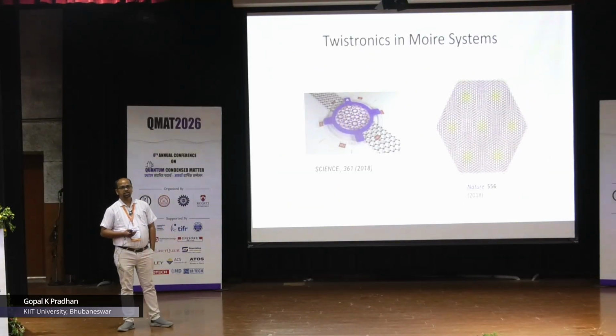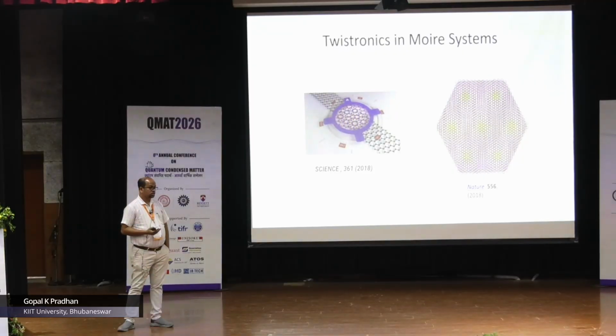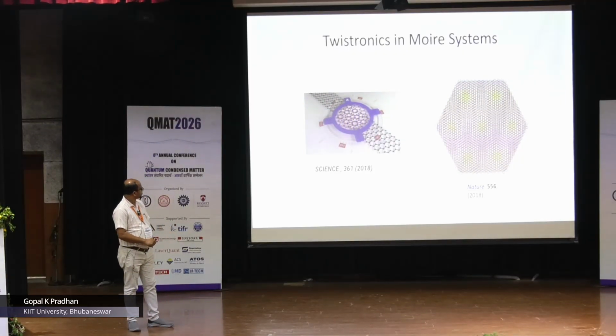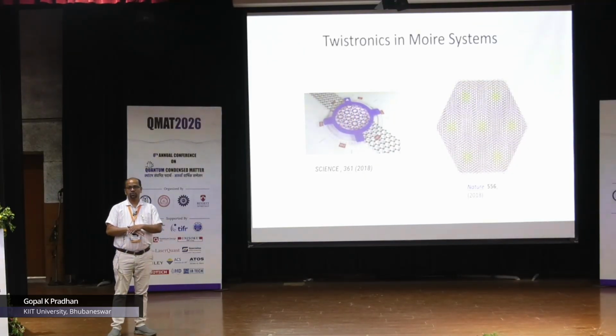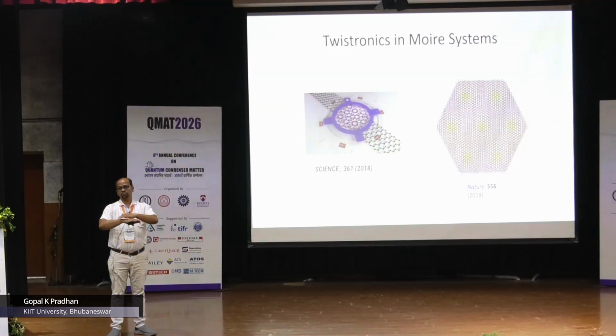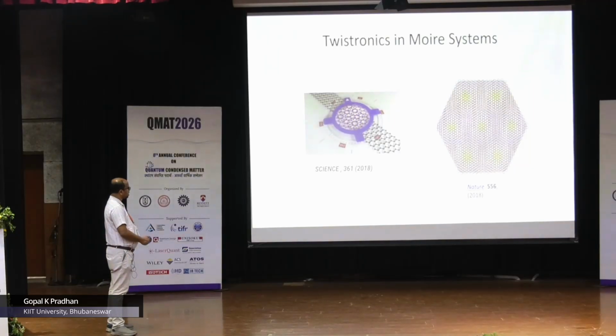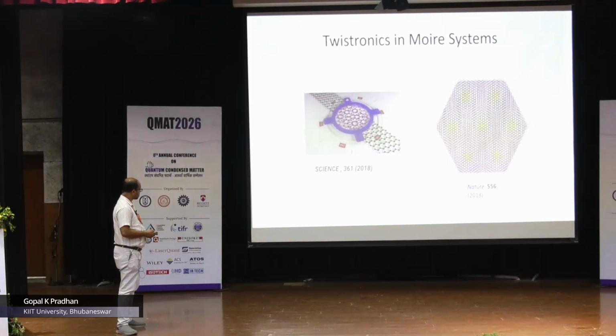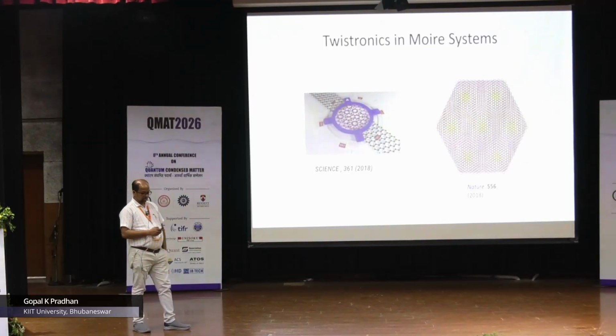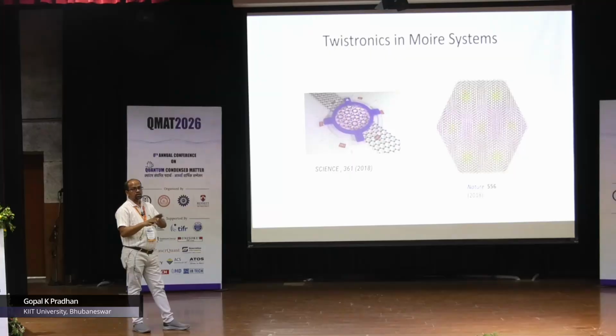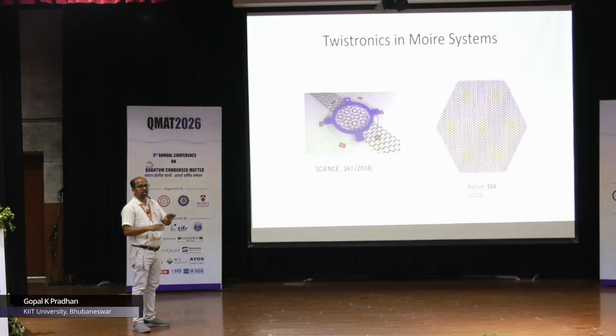There has been a lot of discussion in the last 2-3 days about something called a Moiré system, and these are people who have reported very interesting results, that you can go from a normal phase to a superconducting phase just by tuning the twist angle between different layers. These patterns are called Moiré patterns, and there is very interesting correlated physics one can study, from a fundamental as well as an application point of view. I want to give you one example where we have used Raman to understand the twist angle dependence and the correlation between phonons, excitons and their interactions, right.